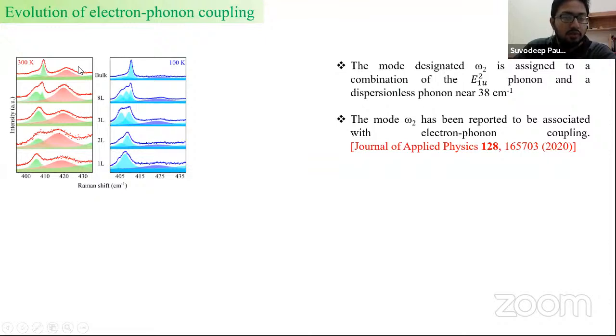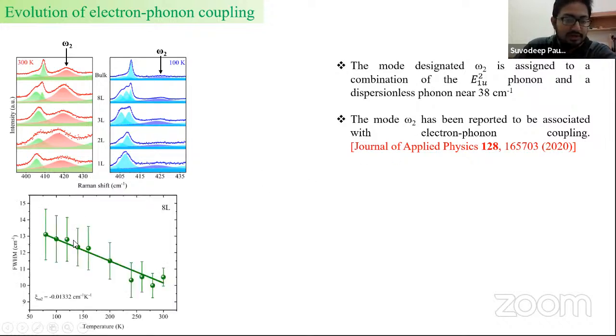We could probe, using resonant Raman, this omega-2 mode. This is a second order mode, which we had to probe with the 633 nanometer laser. And this mode has been previously reported to be associated with electron-phonon coupling. And as expected, we see an anomalous behavior in the evolution of the line width as a function of temperature. It decreases with increasing temperature, and this anomaly is expected for electron-phonon coupled modes.